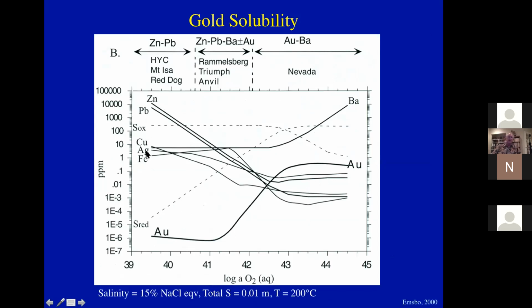The metals have high solubility in these fluids at relatively low log of oxygen concentration. And gold and barium behave exactly the opposite of what most of the metals are doing. As the log of the oxygen concentration goes up, the gold concentration goes up, and the barium concentration goes up. And Paul said, well, you ought to go look at SEDEX deposits that were low in metals and high in barium, and he thinks that's where the gold ought to be.